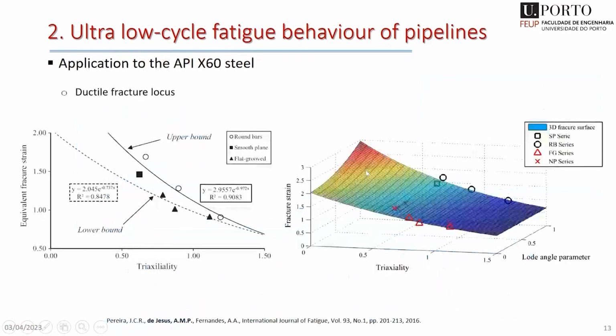So after this, we went to the laboratory and we did some tests in order to identify our model. For that, we will need to run some static fracture tests in order to get the fracture strain. So in this case, you can see for the X60 steel, the fracture locus, where you can see the fracture strain, and this is plotted against triaxiality in one axis, and the load angle parameter in the other. And you can see that the ductility of the material is not a constant. Okay? So we may have a lower bound and an upper bound depending on the stress state, if you are, for example, in plane strain or plane stress, as you for sure know.